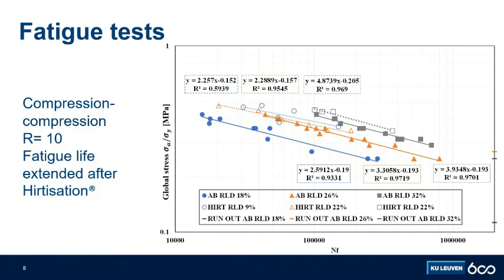So we can see that for the same stress ratio, we can observe a thorough increase in the fatigue lifetime. Or if we think the other way around, for the same lifetime, the Hirtisation treated samples can take up more load.